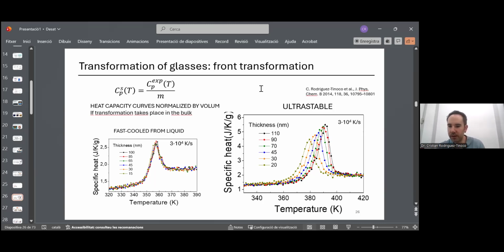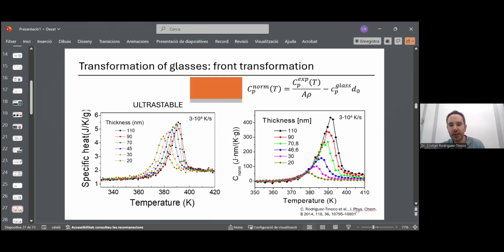Let's say the percentage of the mass involved in the transformation process is not the same in all samples. So if we want to really extract a conclusion about this transformation, we have to use this other normalization protocol we established before. This is dividing by the mass; this is now normalizing in this way, assuming this front propagation. So we see all the calorimetric curves collapse into a single one during the devitrification. So it means that indeed the transformation is proceeding in this way. This is a front which is traveling into the bulk at a given velocity.